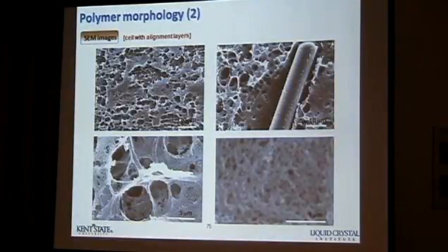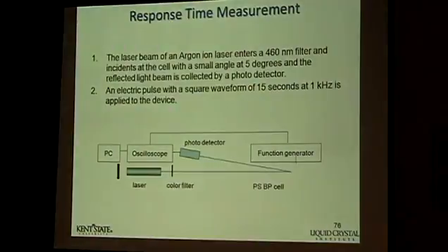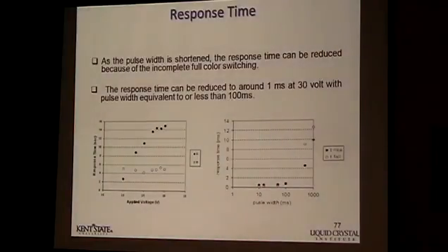It shows these sponge-like structures, and the wall surface is also quite small. I think they are in the submicron range. The holes of those defects are roughly around 5 micron, ranging from 1 to 5 micron. So I guess, response time measurements, we just quickly did that study. It depends on the applied field and voltage, and it can be as short as roughly half a millisecond.